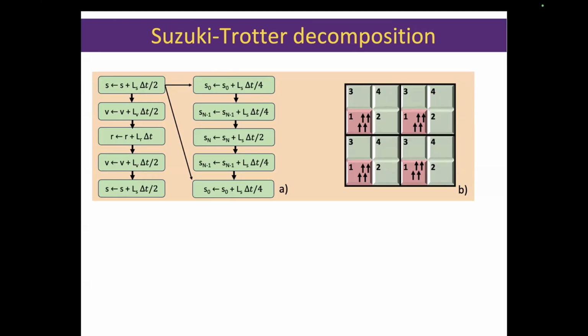Do you manage to do parallel computing with this scheme, or is it not possible? Yes, it is possible to do parallel computing as shown here. This is one schematic for a 2D system. You need to decompose your magnetic part into sectors. When you do the parallel update, you need to make sure that the spins you're updating in those sectors are non-interacting. For example, in this schematic, you can update all of area 1 at the same time, since these are essentially non-interacting. So it's somehow selective parallel computing, and you need to do this extra sectoring.